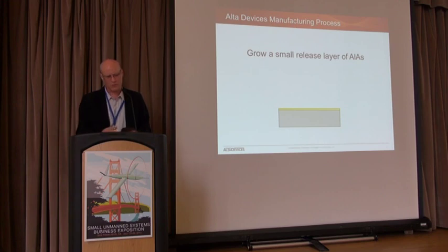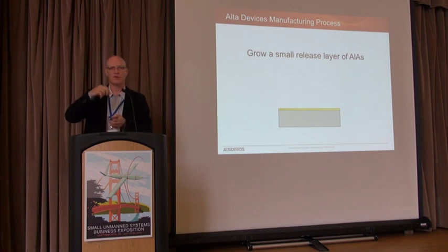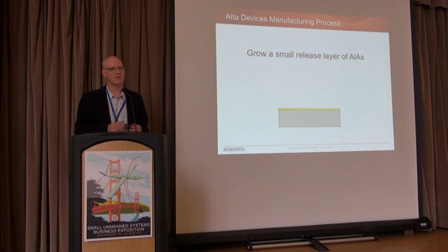And so what happens with this kind of semiconductor material is you can grow different crystals on top of it that have exactly the same crystalline structure. Most of the time, if you have a crystal of one type and you try to put another type on top, they have different lattice constants and they don't fit. You get strain and defects and it just doesn't work. Gallium arsenide is unique because it doesn't do that. There are materials that you can incorporate directly into the same lattice. That's why it's important for the space program, because you can build very high efficiency devices by essentially incorporating multiple solar cells into the same crystalline structure.